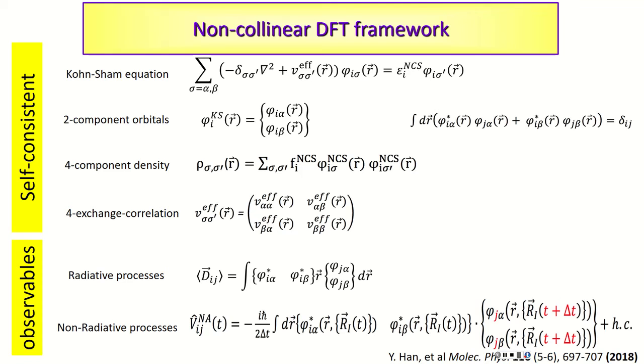If you functionalize your perovskite with transition metal doping with unpaired spins, one needs to have unrestricted DFT. But perovskite itself, even without any magnetic doping, is composed of heavy ions, lead and bromine, and sometimes iodine, and there are relativistic effects and spin orbit coupling. So the spin is not a good quantum number.